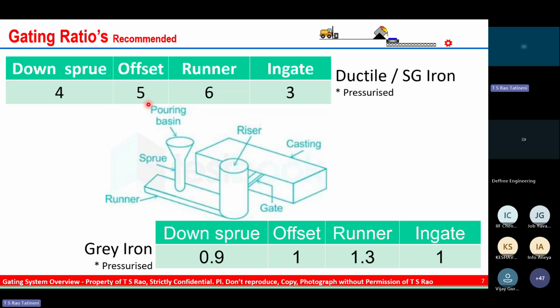Going to the gray iron, if it is a pressurized gating system, it is to be 0.9 is to 1 is to 1.3 is to 1. Again, the offset is very important. The offset should be either equal to or a little larger than the in-gate size.